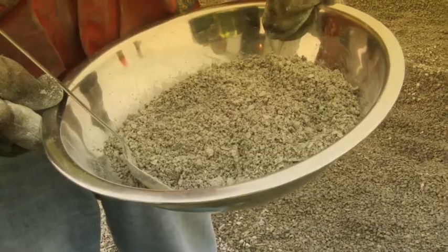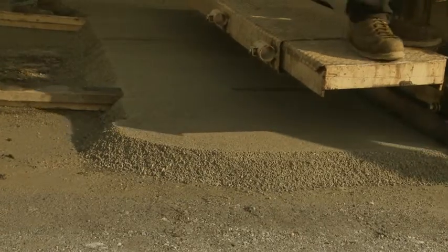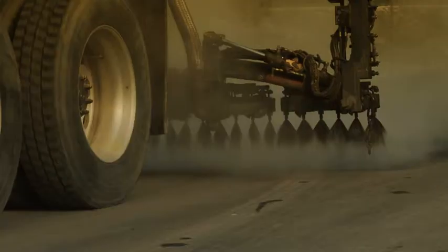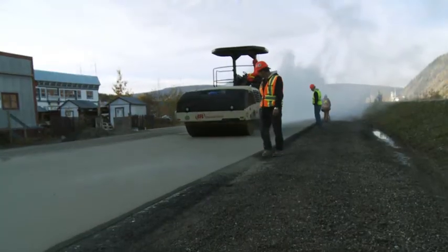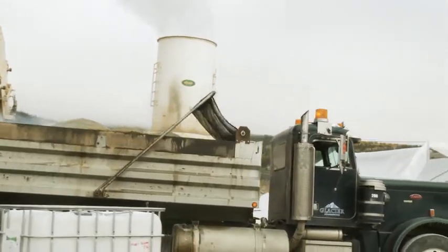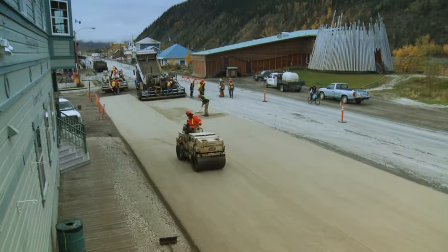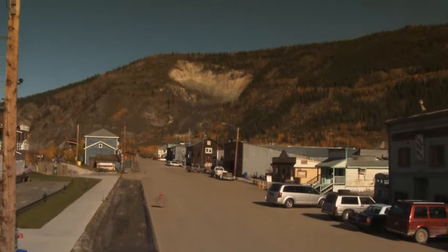On September 10th, the first batch of Bituclair-based asphalt was produced at the Skookum plant, and the paving crew applied a trial layer that same day. After a thin adhesive layer of emulsion was applied upon the black asphalt, the Skookum crew could start the light-colored paving operations. The job continued smoothly and was completed on September 20th, 2009. This first breakthrough project of paving a road with Bituclair in North America opens new horizons for the Colas Group in both the architectural and environmental fields.